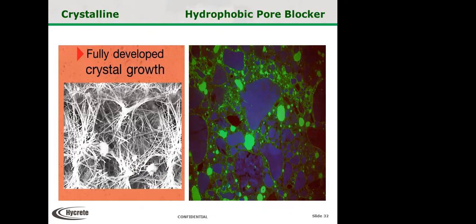So this is one of my favorite slides. This really shows you the side-by-side comparison of the fully developed crystal growth product inside the concrete, inside of a capillary or a pore, versus the hydrophobic pore blocker on the right, which is again filling up all of the potential voids with a less than 1% water absorption. Whereas with the crystal growth, yes, it is going to build more crystals over time. It's going to max out, and it can only grow to a certain point. So you're still going to have voids. It's going to slow the water down, but it can't stop the water. And it requires the water absorption to actually grow the crystals to function and do their job.